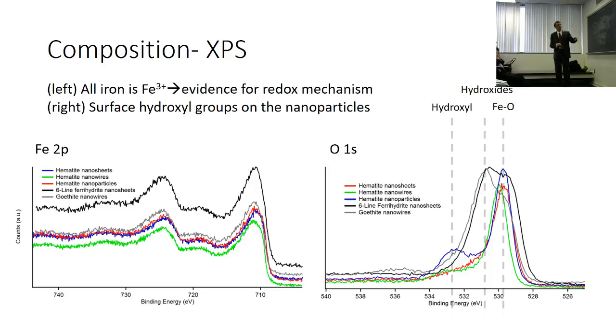Second thing to keep in mind is if you look on the oxygen side of the spectrum, first is this iron-oxygen binding, very important in iron oxide. The hydroxide also has it. Interestingly, the nanoparticles have this extra hump here, which corresponds to hydroxyls on the surface, and the nanosheets and nanowires don't really have that. Is it important? Maybe.